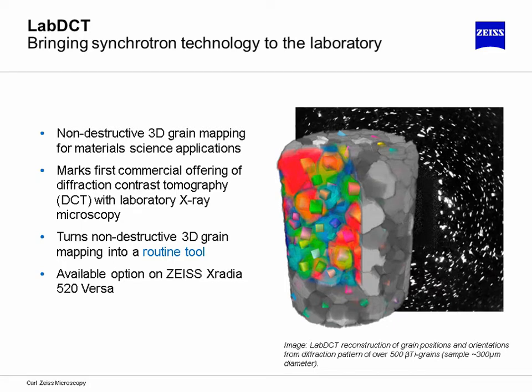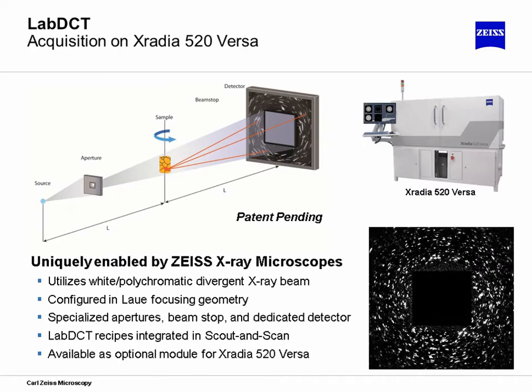Now, for a few minutes, I want to touch on another emerging modality which was recently developed and launched on the VERSA platform, known as laboratory diffraction contrast tomography, really with the vision to turn 3D grain mapping into a routine tool. Using this technique and obtaining diffraction patterns in the X-ray microscope, we can fully reconstruct this into a 3D volume that gives us the grain centers, the grain orientation, and the volume of those grains. Where traditionally in absorption contrast, you would have no contrast from a single-phase polycrystalline sample. This unlocks the ability now to look at the effect that crystallography has on various mechanisms, either failure mechanisms like stress corrosion cracking or different failures, as well as growth, perhaps grain growth studies as well.